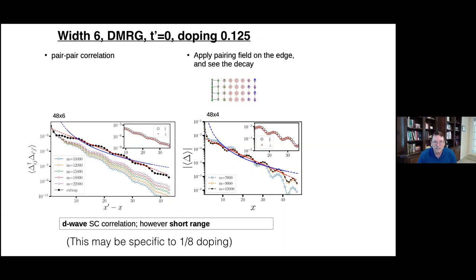First let me show you Chaomin Chung's DMRG with the best techniques. The bond dimension you can see in these calculations is up to 22,000, which is very impressive. We're looking at the pairing response on a width 6 ladder with doping 1/8. Even with 22,000 states, you haven't really converged in terms of the pairing correlations. There's still an extrapolation that you have to do. Once you do that, you can look at this and decide whether these pairing correlations are decaying as an exponential form or as a power law. And they look like they're decaying as an exponential form.